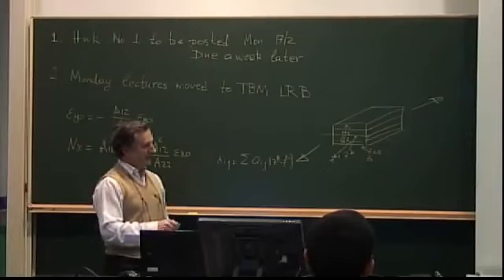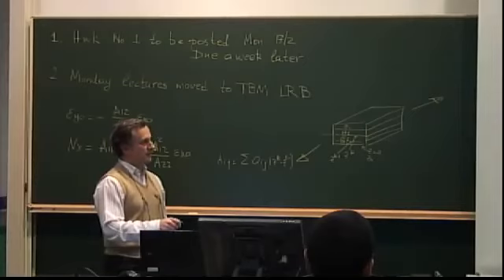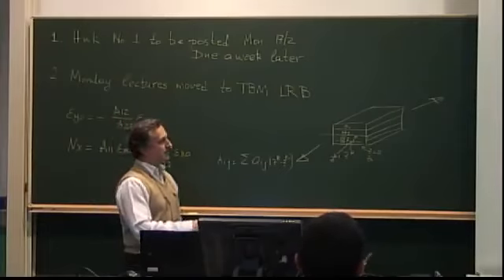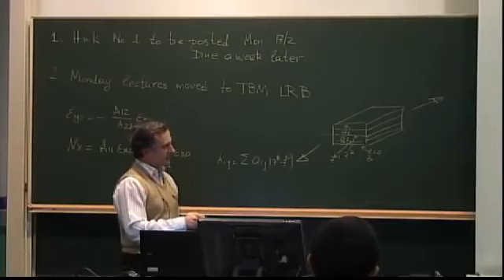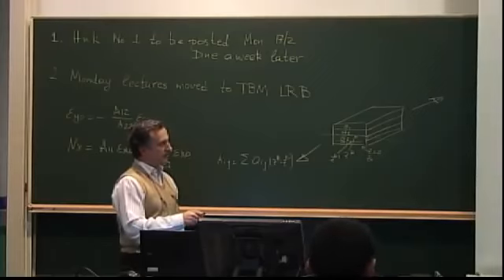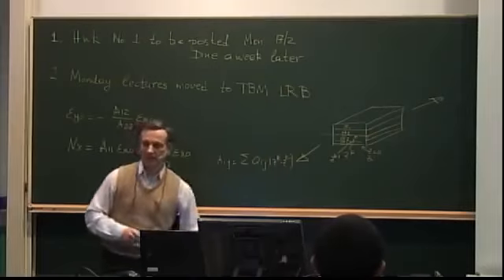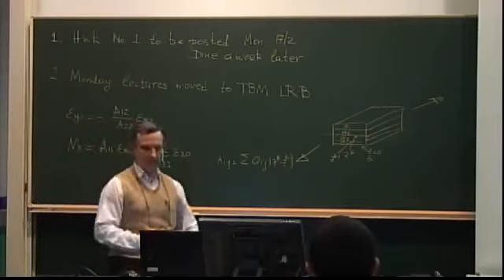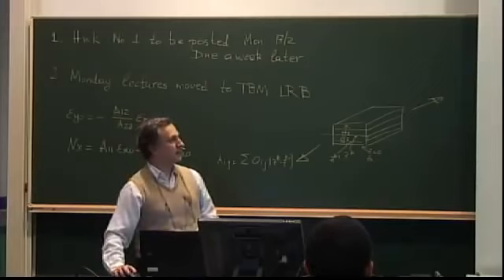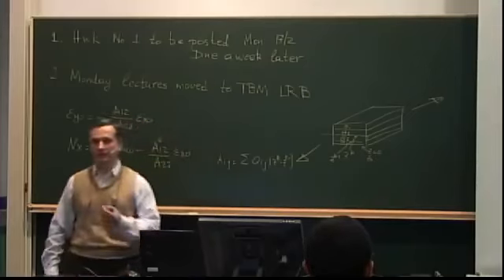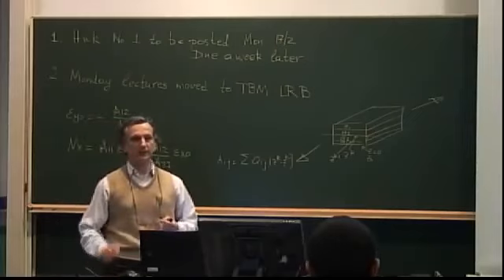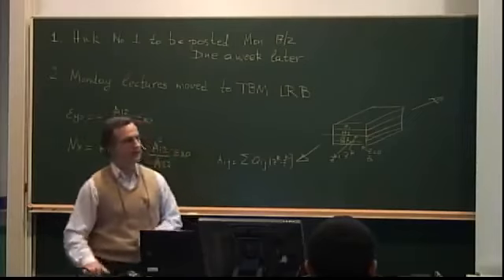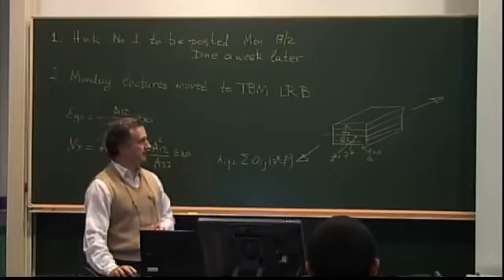And even if I break this here, all that means is somehow I take the load that was in this bottom right portion, transfer it through the very stiff fibers here, and bring it back into the structure or the ply behind this crack. And you can do the same thing here, unless there are cases where you have delaminations, which means you cannot take load from here to here now because they have separated. So the mechanisms are there, and I'm trying to indicate that there are multiple mechanisms, and what happens first is not necessarily what relates even to what happens last. Or if it does, it's a fairly complex process going from one failure mode to the next.